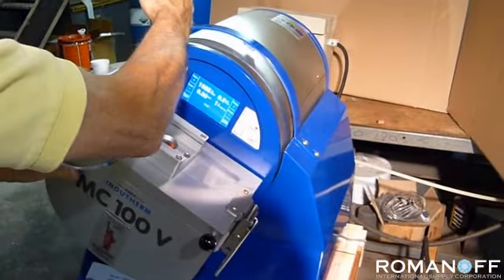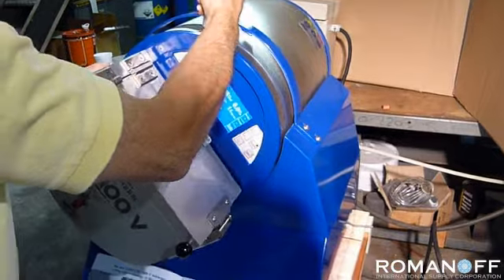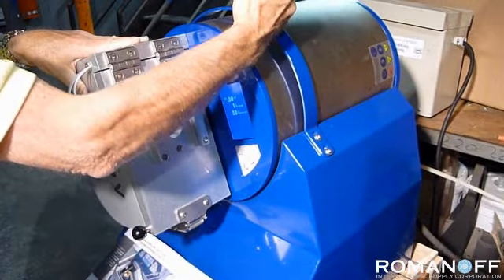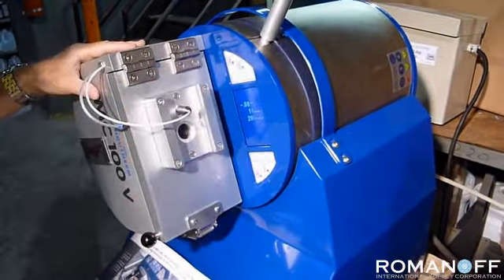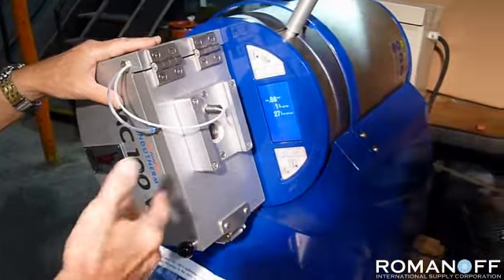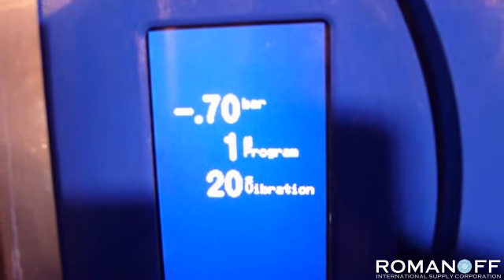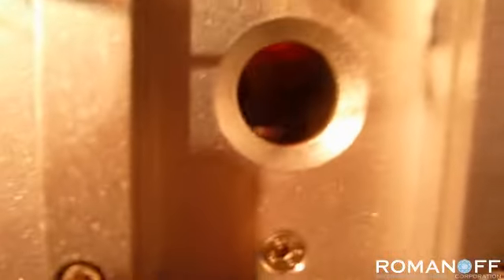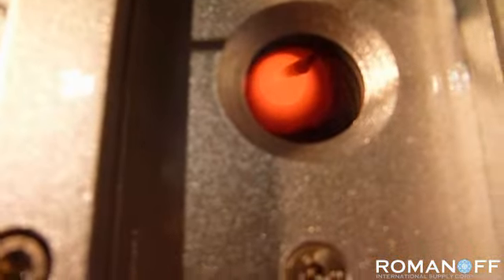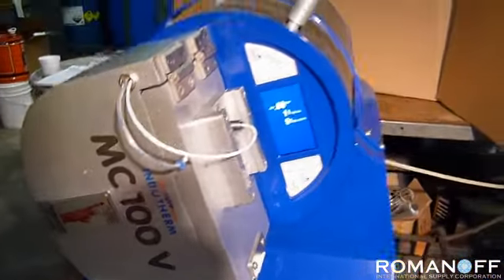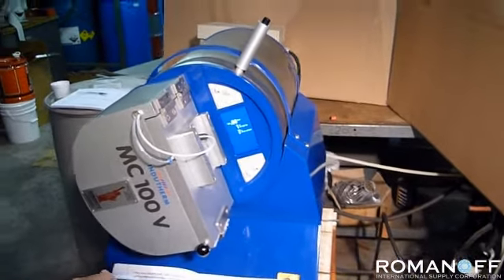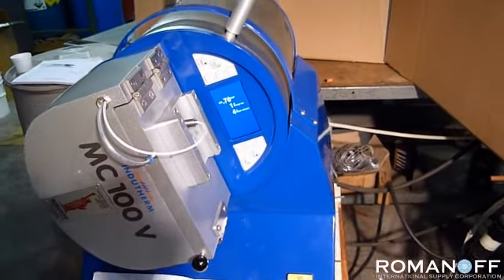We begin casting by tilting the chamber over slowly. When it reaches a certain point, the pressure begins and the vibration will be on for 35 seconds, which is what we have it set for. In fact, it's indicating now the amount of vibration time, which is going to go down to 0. The power is off and the metal is cooling and solidifying while the vibration is on, and also under pressure. So you should end up with a very dense casting.